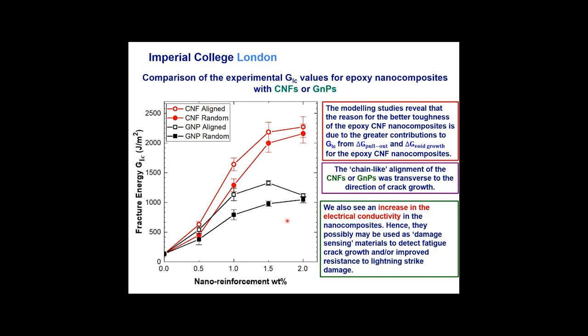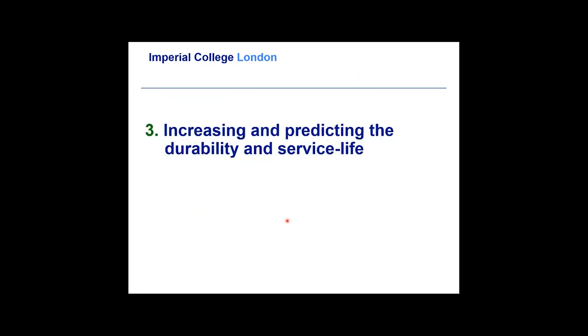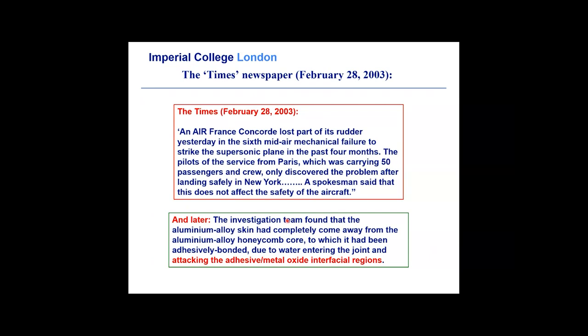We also see, as you might expect, an increase in electrical conductivity in the nanocomposites. Hence, they can be used as damage sensing materials to detect fatigue crack growth, or possibly improve resistance to lightning strike damage. So it gives you really a multi-purpose adhesive that not only is tougher, but has other applications too.